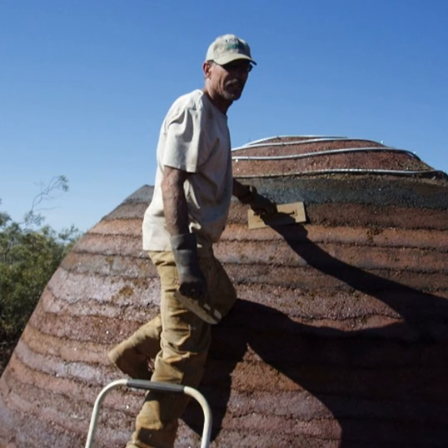Let me just briefly interject and say, one of the problems with Portland cement, back to the aggregate issue, is that when crushed up glass is used as an aggregate with Portland cement, it doesn't work so well. There is a reaction, a bad reaction, called the alkali silica reaction. Portland cement is so alkaline that it partially dissolves glass and creates a weak bond. And that's what this so-called alkali silica reaction is. There is no such reaction with Ferrock.